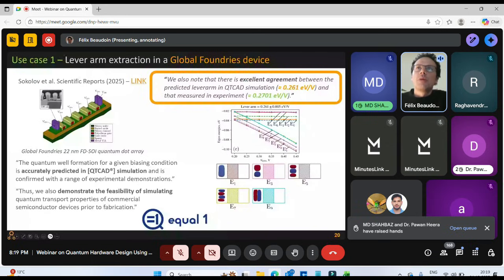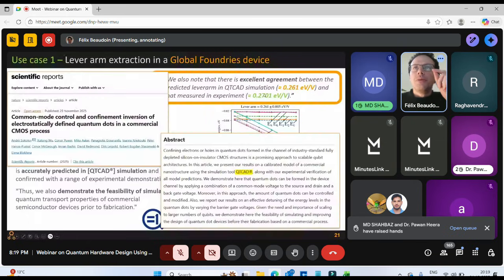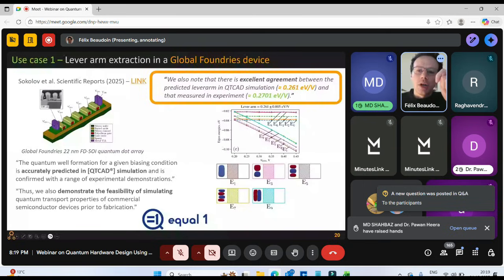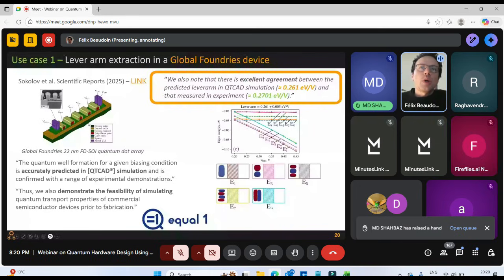They found a lever arm of 0.261 electron volts per volt, which compares within a few percent to 0.27 electron volts per volt measured experimentally. So this not only shows that you can actually model these systems, but you can model them quantitatively with QTCAD. And the fact that they could get the same lever arm also means that the quantum dots that they got were formed electrostatically as expected from the design, which is non-trivial. Sometimes people get spurious quantum dots in those kinds of devices. So this really shows that they're doing what they want. And eventually, as they scale up, they will be able to use the software to skip a lot of trial and error. This was accepted in Scientific Reports very recently.